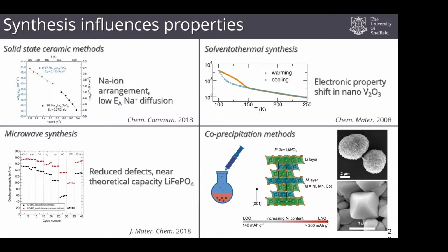The other thing that we can do is we can make crystals of these materials. Why would we want to do that? If you look at something that's polycrystalline like this, where you have all these little primary particles dotted together in a secondary assembly, every time lithium moves in and out of that structure, these particles, their volume can change ever so slightly. So these are constantly changing volume. And sometimes that can lead to a crack through that particle. If you use a single crystal, you're less likely to get those cracks. And so you may have seen some news stories a few years ago of the million mile battery. And that was based on these sorts of single crystals used for nickel-rich materials.